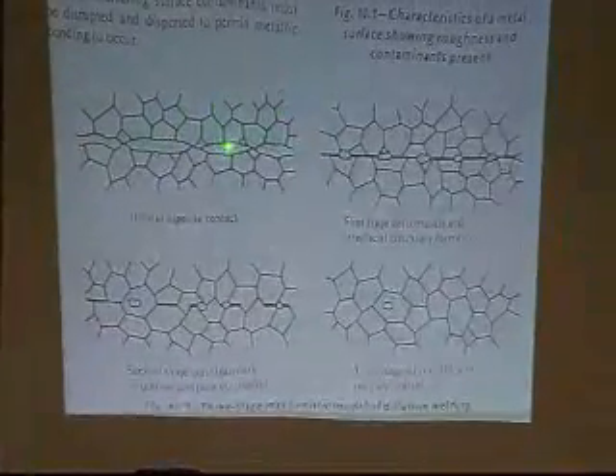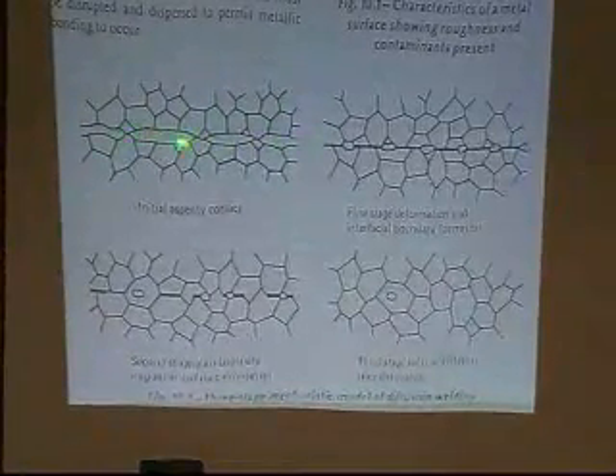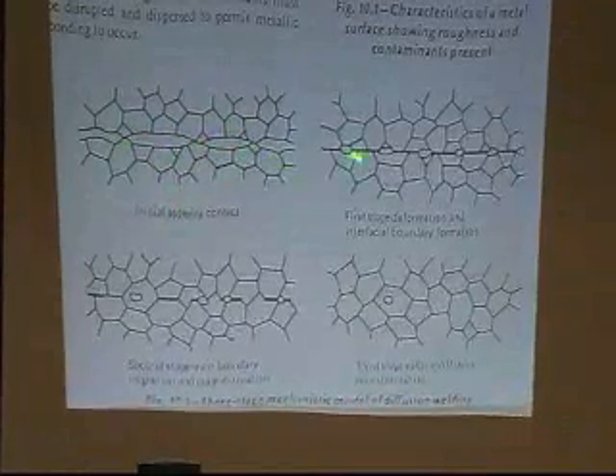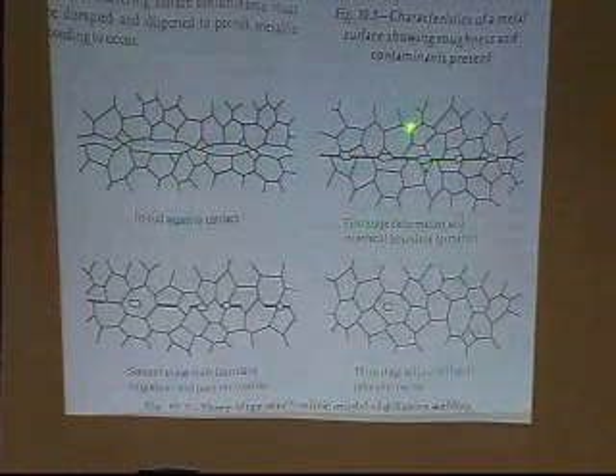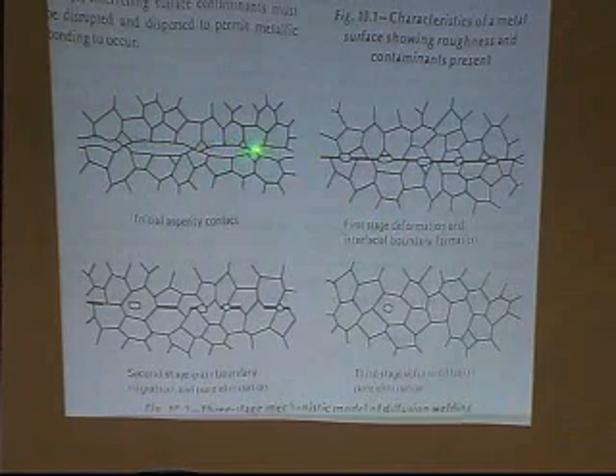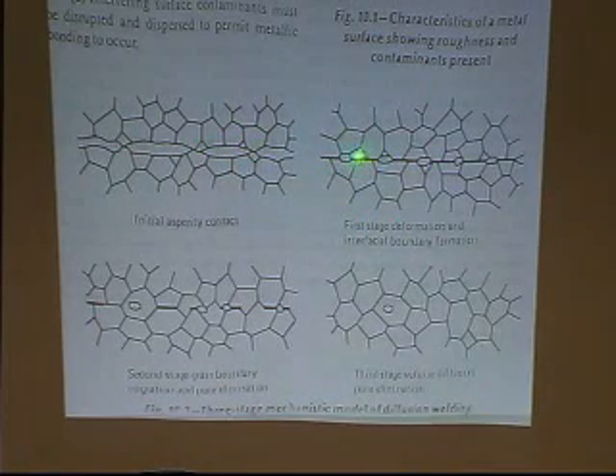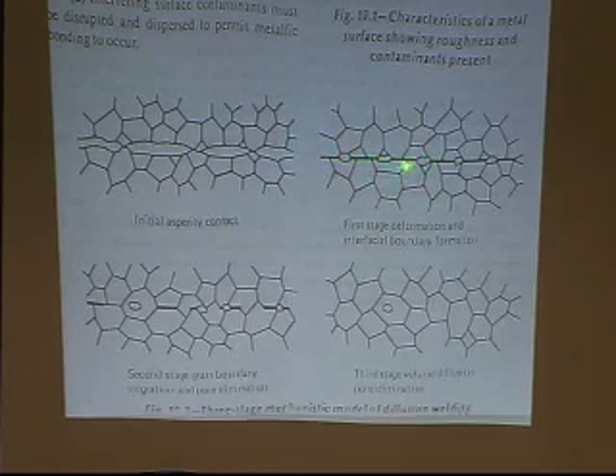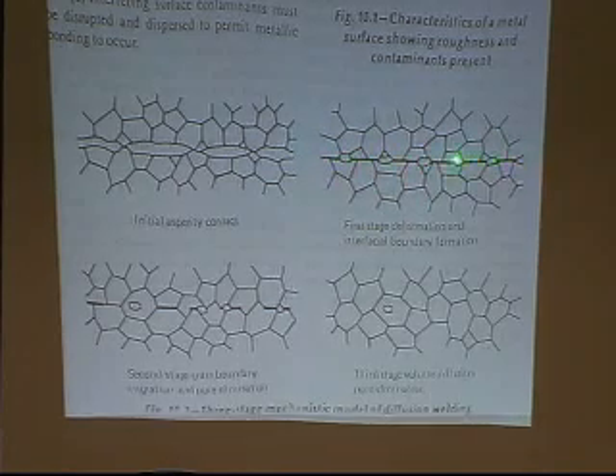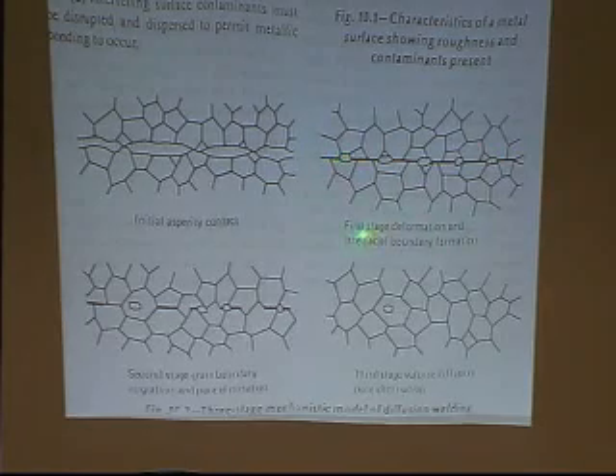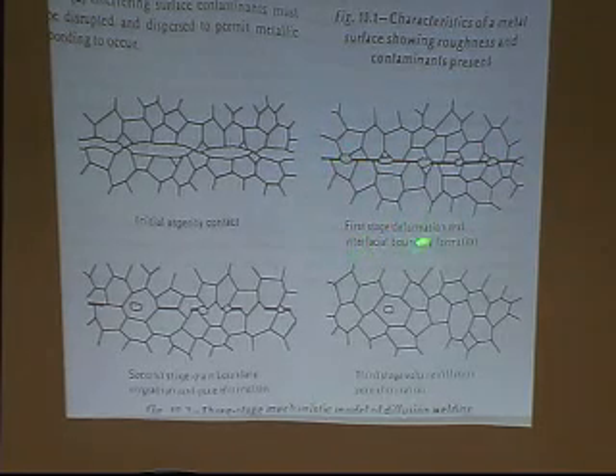I think we have. And here they have the 4 stages of diffusion bonding, as they call it. Initially, these are the grains in the metal, and these are the pores. And you have asperity contact, this is initial asperity contact. The first stage is where you've got pressure that squeezes these little touching mountain peaks together, and you get deformation, and so you get flat areas. And now you have pores, and you have a bond line here in the center, but you've got pores right along the bond line. And it says first stage: deformation and interfacial boundary formation.